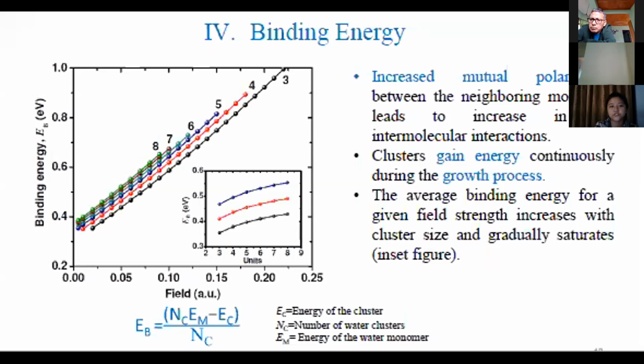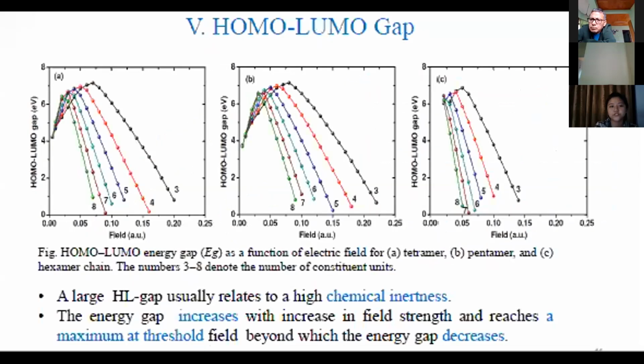Next, we come to the HOMO-LUMO gap. And as we know, the HOMO-LUMO gap is an important index for measuring the chemical stability of the system. So this first plot is for the tetramer chain, the second is for pentamer, and the third is for hexamer. Here we see that the HOMO-LUMO gap increases with increase in the field. That means the chemical inertness of the system increases. It reaches the maximum at one particular field, and then it starts to close. This particular field at which the HOMO-LUMO gap starts to decrease, we call the threshold field.